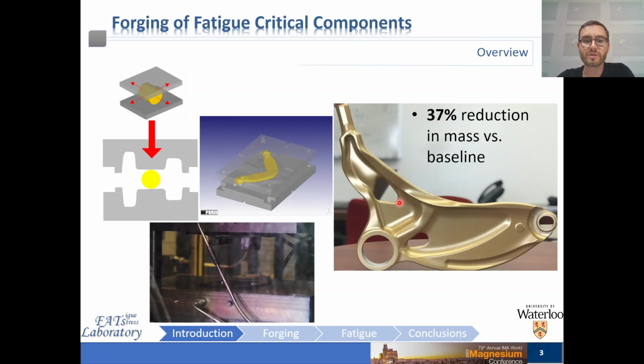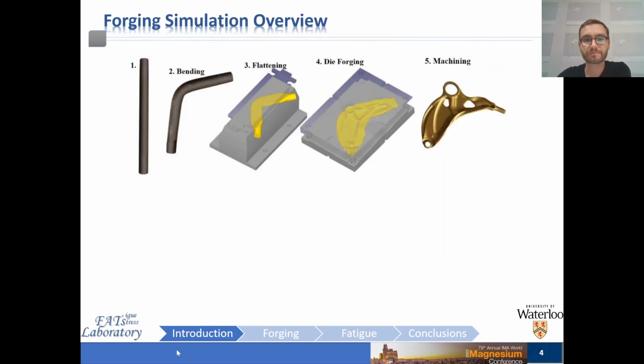However, it was only possible due to the experimental methods which we adopted to optimize all the facets of the research process. On the left-hand side of the slide, you can see a schematic of the forging process where intense pressure between rigid dies forces the material to flow in the internal cavities and conform to the desired geometry. This can have many beneficial effects for fatigue, as well as some detrimental ones if the process is not carefully managed, as is done at moderate temperatures between 250 and 450 degrees Celsius.